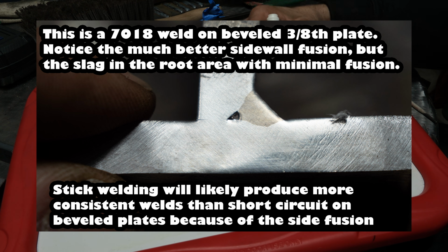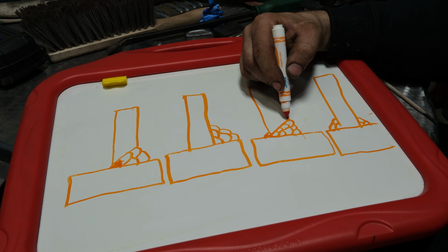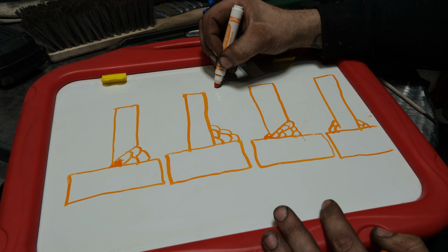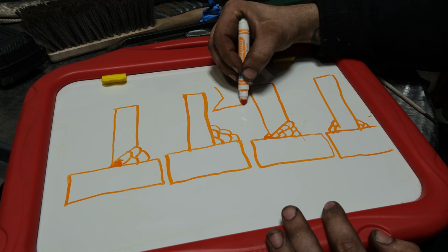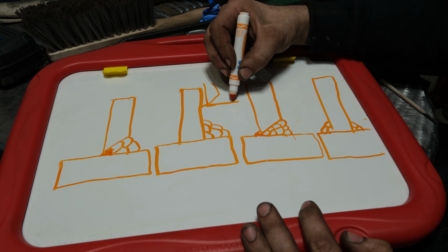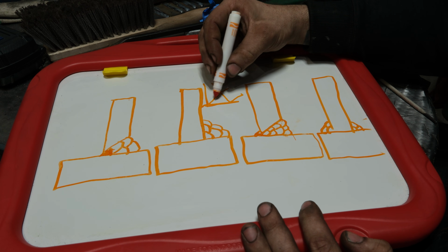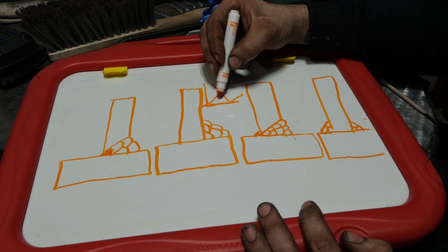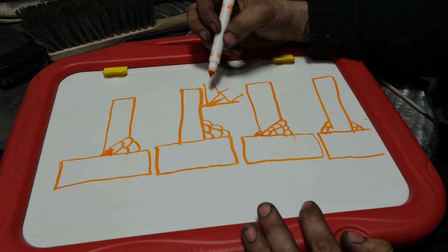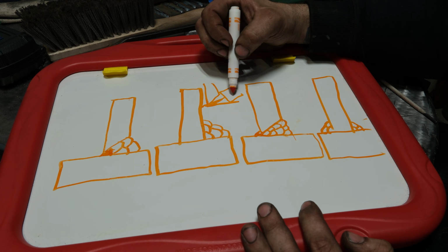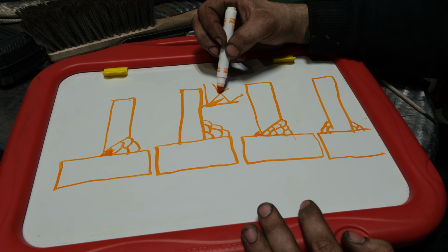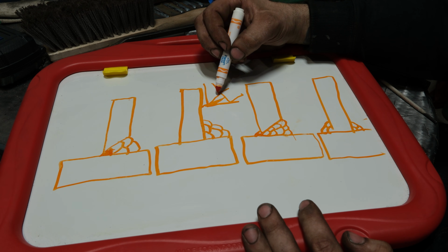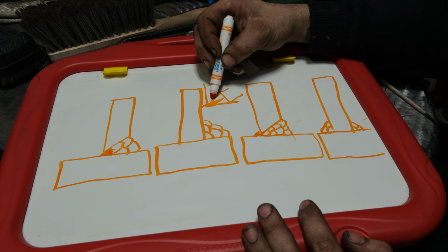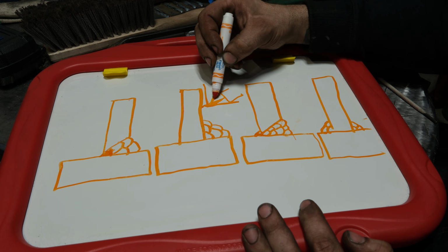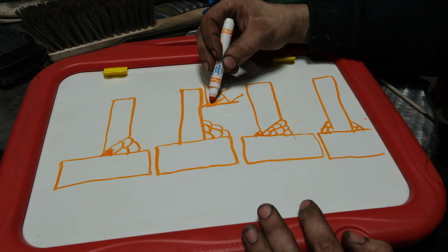Not to mention, when you start dealing with really odd bevel sizes, what'll happen is, and I'll depict it right here. So this is the bevel. Your stick electrode may be this wide. Okay, this is obviously not drawn to scale. And what happens is that you effectively get a really long arc gap in here, and you can create undercut and slag inclusions, and the rod runs poorly, and you get arc wandering. So with stick welding bevels, it's super critical that your bevel is wide enough that your rod fits in there to where you don't have a massively big arc gap.